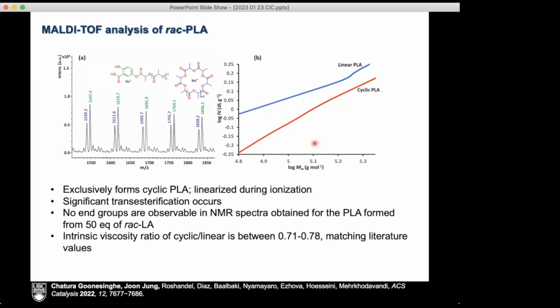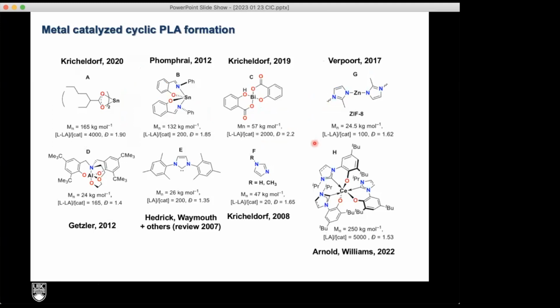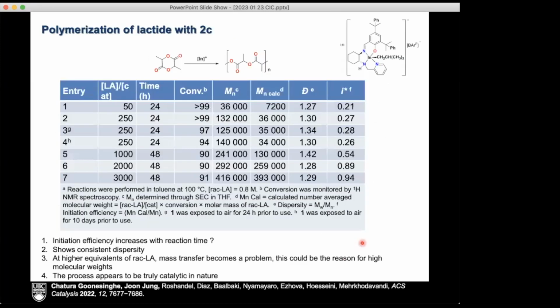And this is actually relatively rare. There are systems that do make cyclic PLA, but they don't give you very high molecular weight material. Right around when we were ready to submit our paper, Arnold and Williams published this one for a cerium complex for making high molecular weight cyclic PLA. Interestingly, the mechanism is very similar to ours. Our paper was also published in 2022.